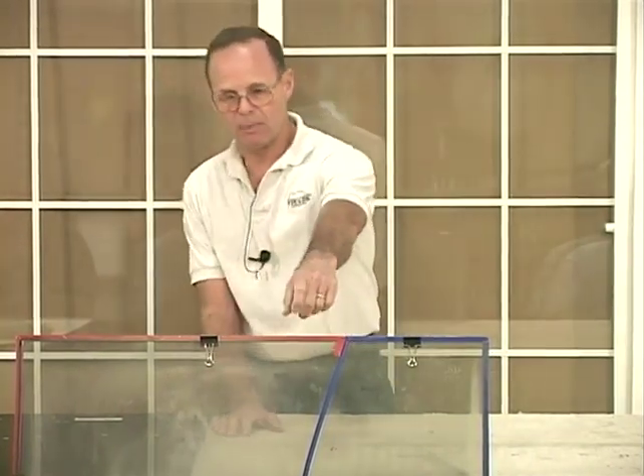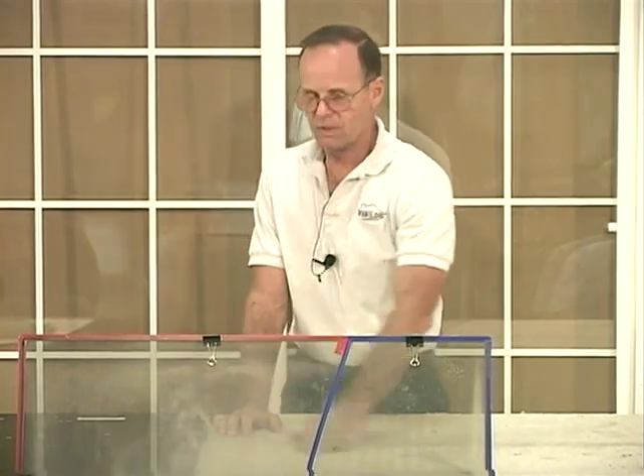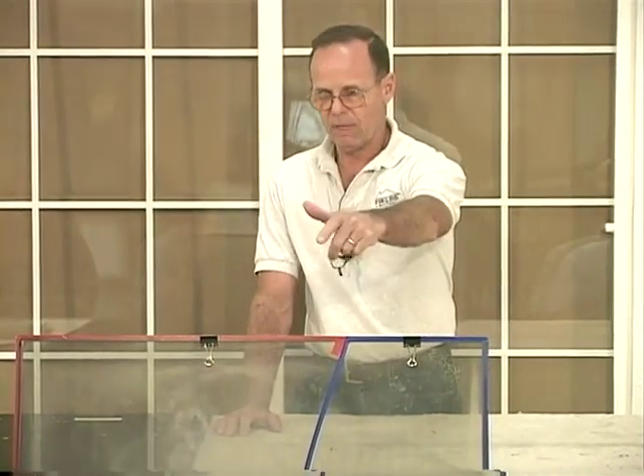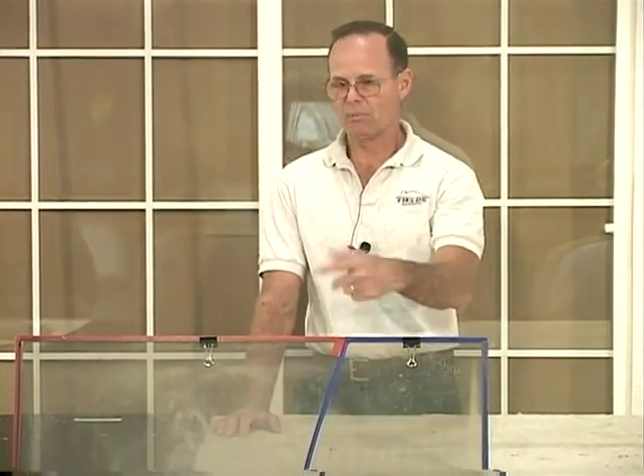Both of these inside panes here, I tested with the UV lamp earlier, and both inside panes are on the air side. And when I pulled that apart, they were both corroded. But a lot of IG units, if you look at them close, only one pane is corroded and the other one's not. That's because one of them, the tin surface is facing out. And if you take a UV lamp, you can test it and it'll confirm that.